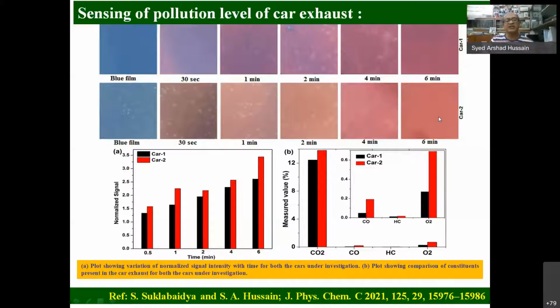But for quantification, we analyze the normalized signal intensity, and you can see the comparison of 2 cars. One is black, one is red. You see for car 2, in red, the extent of polymerization is higher at all times. Then we checked the pollution level of the car using a standard system available in the market, and we analyzed the components in the car exhaust, say CO2, CO, HC, O2, etc., and compared for both cars. Based on the concentration of CO2, CO, HC, O2, etc., polymerization is linearly affected. So that means with proper calibration, it's possible to have an idea about the exhaust level or pollution level of the car using our clay organic PDA as well as imidazole systems, and it's simple, a paper kind of thing.